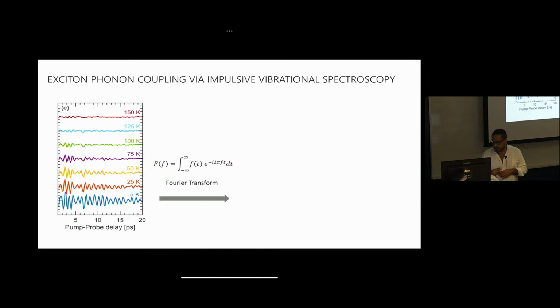Then you take the signal. So here it is. You take a cut along a particular probe wavelength, and you have this oscillatory response. You see this ringing. You see several modes. There's a strong temperature dependence. That's what Esteban is going to tell us a little bit about in a moment. But let's look at 5 Kelvin. You've got this ringing response. This is just a Raman spectrum in the time domain.